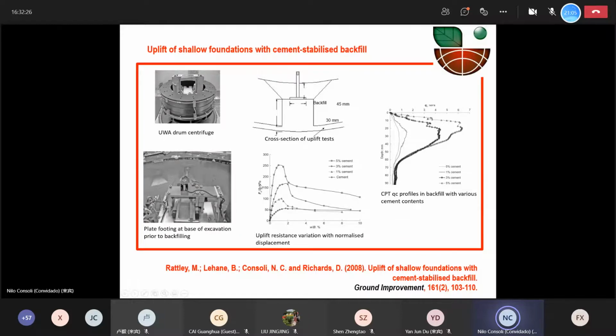And if we put 5% of cement, we multiply by 5 the peak pull-out capacity that we have in this soil. We also have tested some CPT tests inside the centrifuge, showing how it improves. So this paper was interesting because we have shown, even though it was in a small scale, the capability of improving this backfill in order to raise the uplift capacity of a shallow footing that we have here.